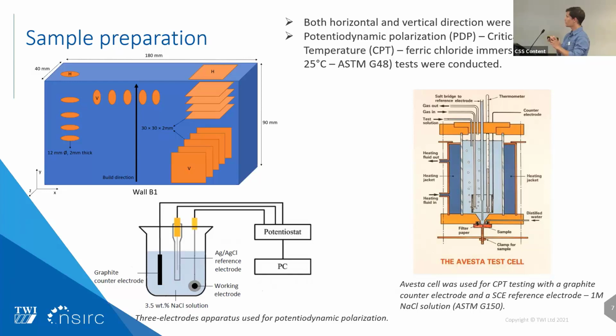Then we have square samples used to do critical pitting temperature tests, or CPT testing. We used an Avesta cell, which you can see here, whose main goal is to reduce the risk of crevice corrosion. We used a saturated calomel electrode as reference and a graphite counter electrode, done in 1 molar sodium chloride solution according to the G150 standard from ASTM.